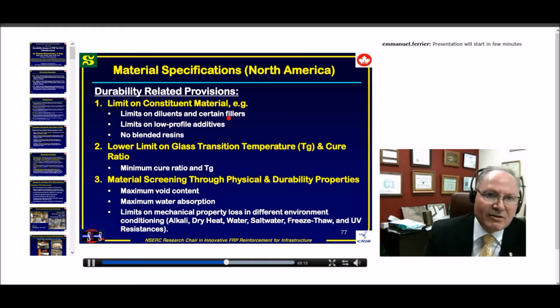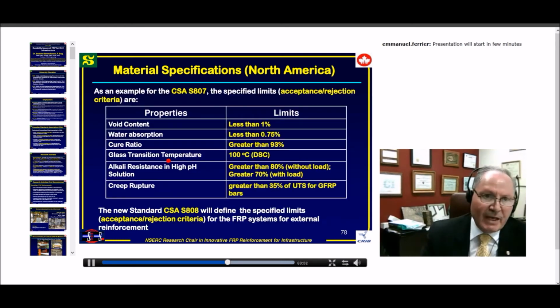We have a limit on diluent and certain fillers, and a limit on low-profile additive. This is mainly used by manufacturers to control shrinkage and so on. Non-blended resin: we are not allowing two types of resin. It has to be the same type and the same category. Lower limit on glass transition temperature and cure time. We are specifying minimum cure ratio and minimum glass transition temperature, and material screening through physical and durability tests, void, water, and so on. Many properties, as you can see here in these slides.